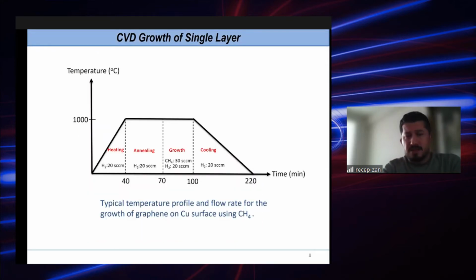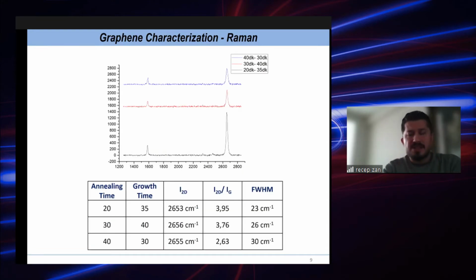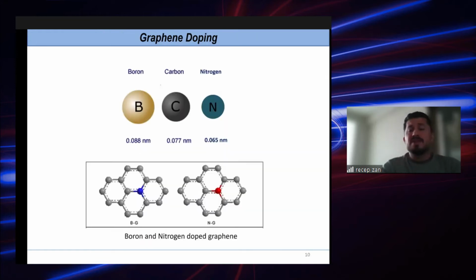And of course, the general synthesis process includes heating, annealing, growth, and cooling. On the characterization side, we mainly use Raman spectroscopy, which is easier for us, a straightforward method, and easy to handle the sample during the measurement. We can also use the sample afterwards. We played with annealing time and growth time, and we check the Raman to make sure that our graphene is homogeneous and single layer. We check the 2D and G peaks, as you see on the screen, their position, their intensity, the ratio between them, and their full width at half maximum. Here's what we did so far for the pristine graphene.